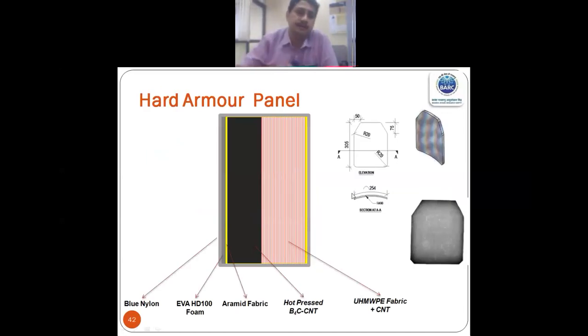As I told, there are hard armor panels and soft armor panels. So for hard armor panels, what is used? It is a sandwich structure where the strike face, that is the bullet face, should have a ceramic, because due to its hardness, the ceramic can blunt the bullet and it gets fractured. Once it gets fractured, the fractured fragments as well as the fractured bullets need to be contained by the back face, this backing material, which is a layered structure of ultra high molecular weight polyethylene and CNT composites. And here we have used boron carbide as the ceramic, as well as a boron carbide CNT composite.